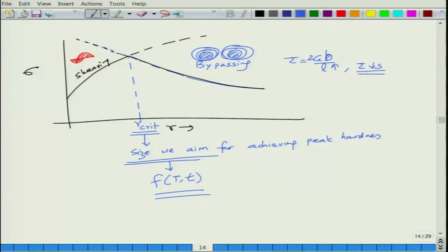And then formation of fine precipitates of optimum size, which leads to maximum strengthening and really hard alloys, especially aluminum copper alloys. You get a very high level of strengthening. The shear stress that you may achieve could be as high as 400 MPa in these alloys, and the corresponding hardness can also be very high. So this is where we will stop now.